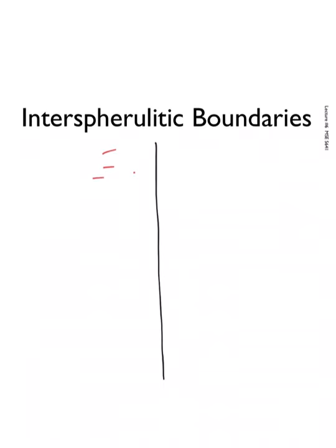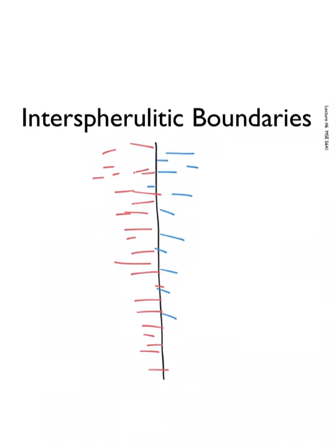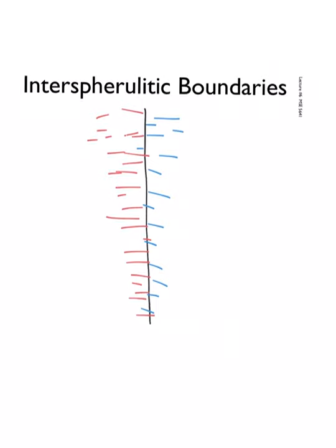We have individual crystals that are stopping and starting, nucleating, growing, and they're reaching this area. And they don't necessarily stop just because somebody sees something in the microscope at a much higher magnification. And then you have the other side, the other spherulite, and that has small crystals that are also reaching that boundary and probably extending over it, because again, they don't care what the person at 30,000 feet is seeing. They're going to do what they're going to do. And so you have this phenomenon known as interdigitation that's occurring at this interface. And what that means is fingers coming together, all right? Fingers extending across the boundary.